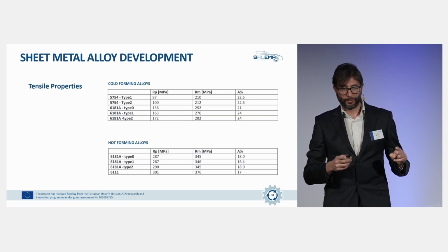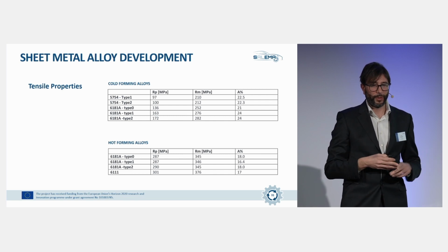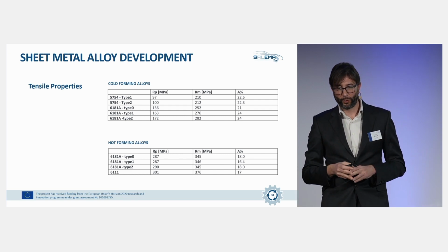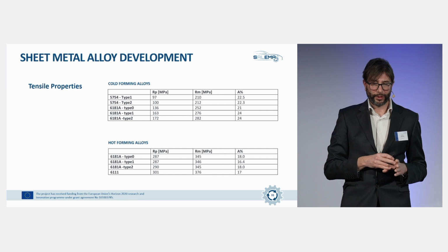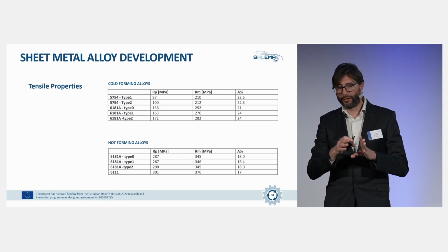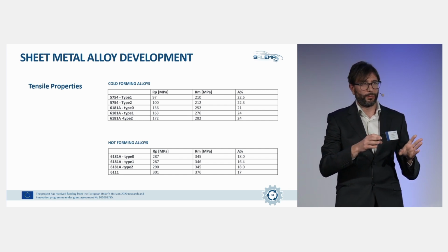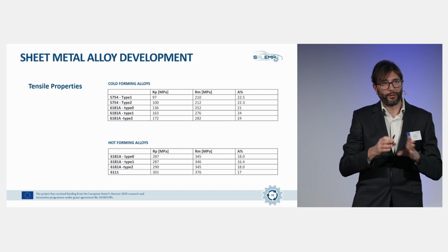So the first thing we did was to measure the tensile properties of those alloys, and we observed that the static property values remain unaffected, independently of the scrap rate used to produce the alloys. Elongation was very high, even with 85% of scrap, in both alloys, 6181 and 5754.